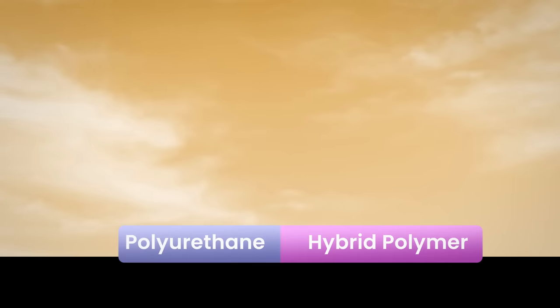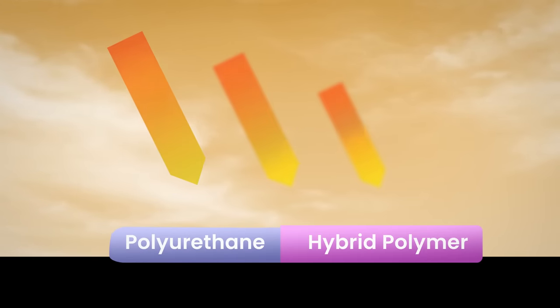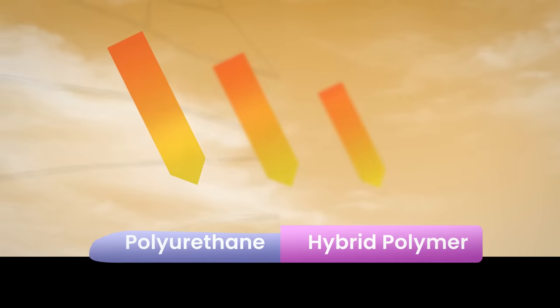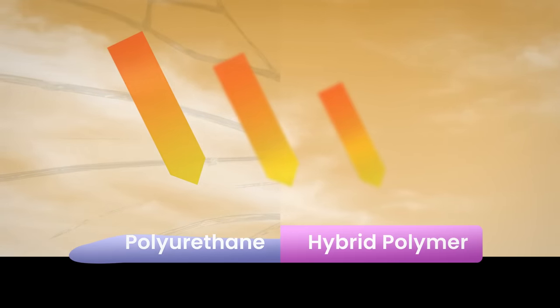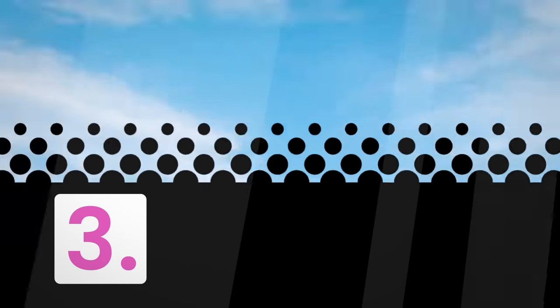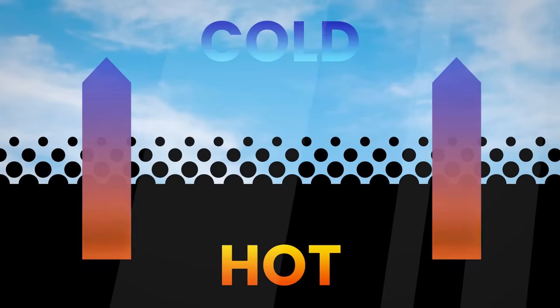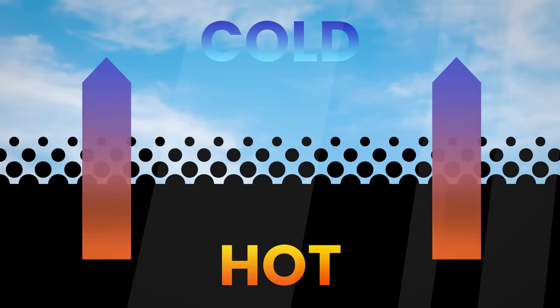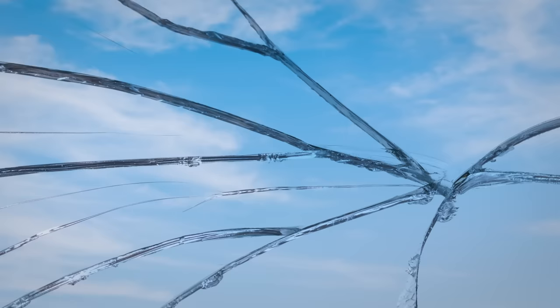If this adhesive is made out of polyurethane, which most glass bonding adhesives are, it can become weaker after continual exposure to direct sunlight. Hybrid polymer-based adhesives handle sunlight much better as they have more UV resistance. The halftone pattern in which the black dots are scattered helps distribute the temperature evenly and helps prevent optical distortion or lensing that would potentially shatter the glass. The frit also provides a more polished appearance by concealing the adhesive bond.